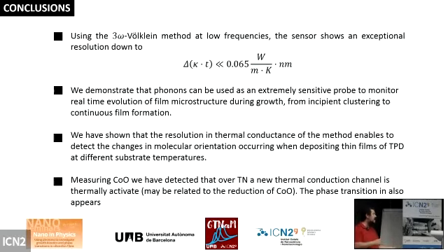And at the end, we have measured cobalt oxide, and we have detected that above TN, the thermal conductance channel is activated, but maybe it's activated because we are reducing cobalt oxide and getting metallic cobalt that is quite more conductive, and that the phase transition also appears in the measurement.